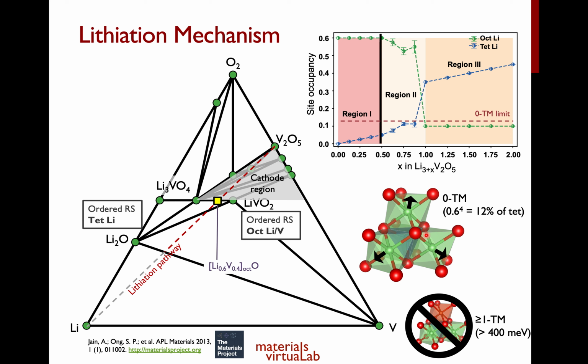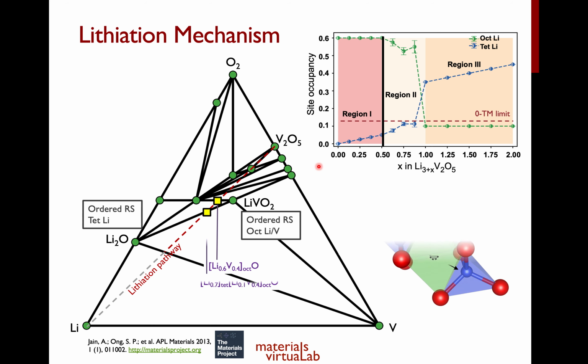You are basically inserting lithium into tetrahedral sites, which is why you see this increase in tetrahedral lithium occupancy, while your octahedral lithium occupancy still remains constant. So you have displacements of lithium, but the occupancy actually does not change, right? This happens all the way up to about Li3.5V2O5 or so. Now as you continue to lithiate, between Li3.5 and Li4V2O5, you basically have the increased electrostatics from many lithium being inserted into the tetrahedral sites begin to force some of the octahedral lithium into other tetrahedral sites.